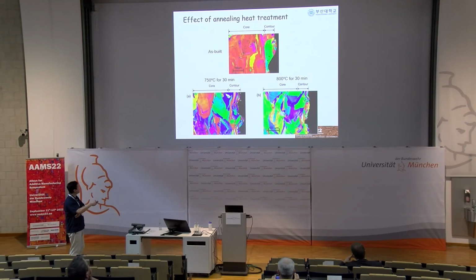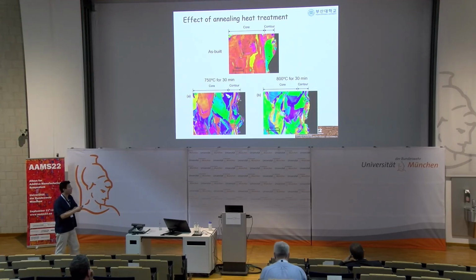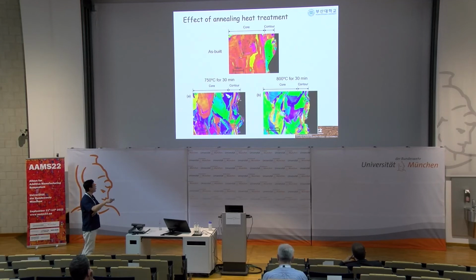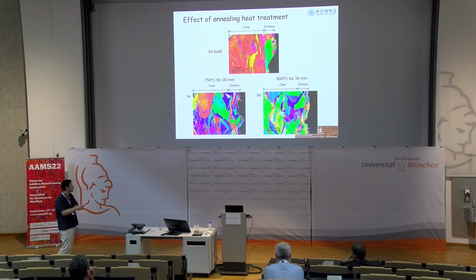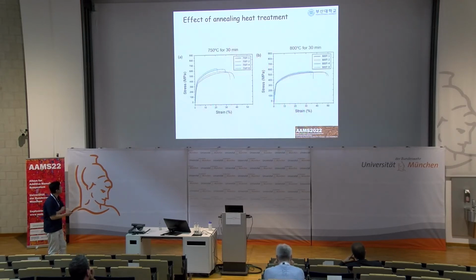I didn't bring any optical micrographs, but this condition, 750 degrees for 30 minutes, we call internally the stress relieving heat treatment, where we don't change any microstructure, but we don't have any distortion anymore. And in this case, we call it the homogenization heat treatment, where we diffuse the solidification cells. So we selected two different conditions and checked the mechanical properties again.